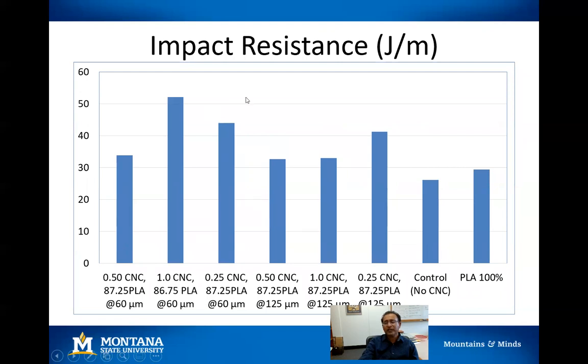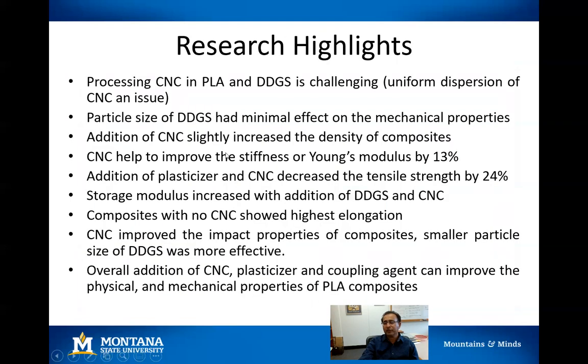Another important weakness is the impact resistance of polylactic acid polymer. So when we added CNC into it, we can see that the impact resistance of these composites went up. And so this is a 100% commercial PLA. This is without cellulose crystals. So definitely, addition of cellulose crystal helps to improve the impact properties.